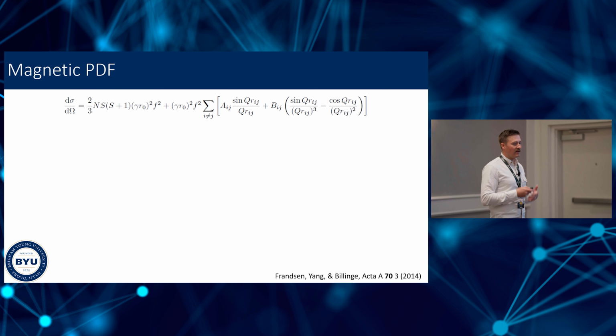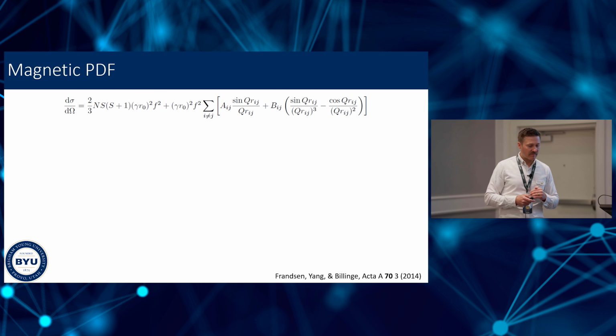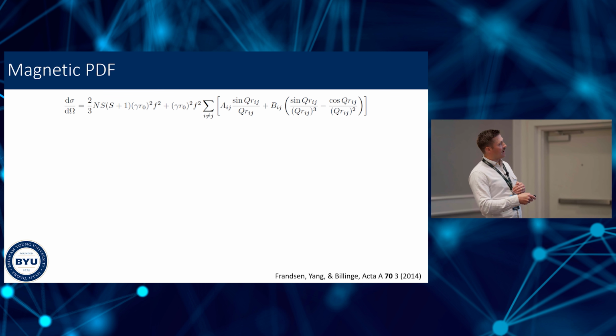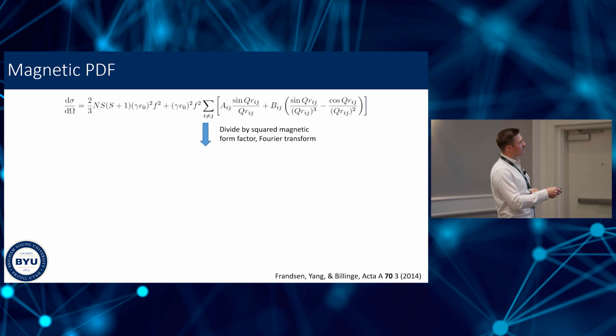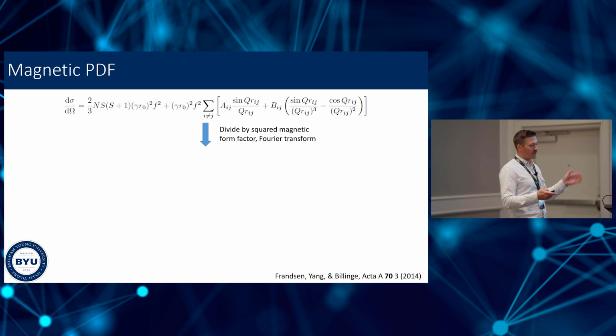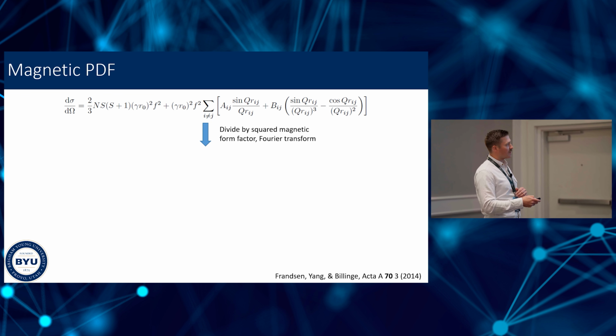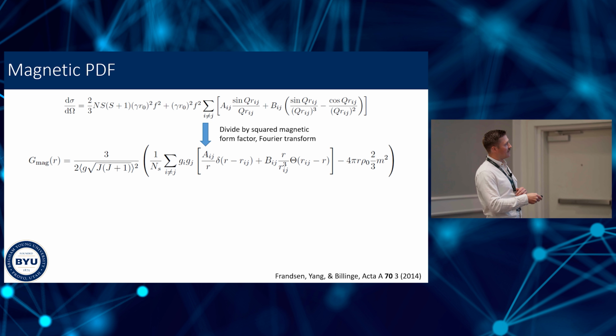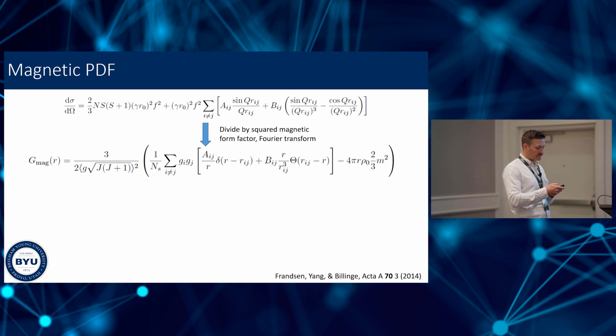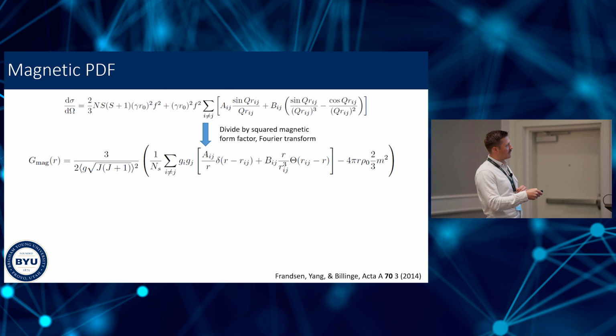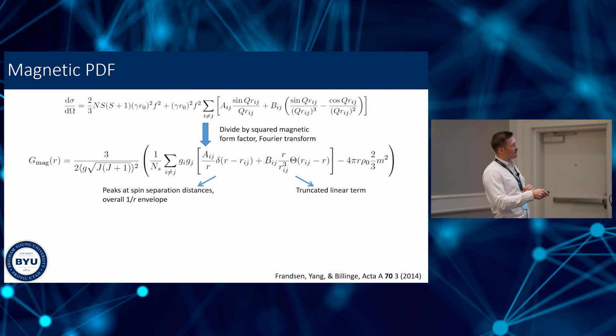And it's, in the end, a straightforward analogy to atomic PDF. You start with the magnetic differential scattering cross-section. This is expressed here just in terms of magnetic moments and their orientations and positions, not assuming anything about periodicity. And you just divide by the squared magnetic form factor, you compute the Fourier transform. The details are not so important, but you end up with an expression that looks like this, a nice closed form expression. And it has a series of delta functions which occur at the distances separating pairs of spins.